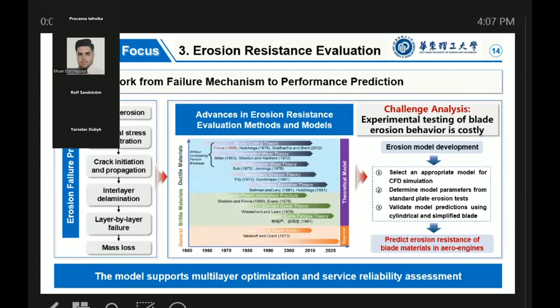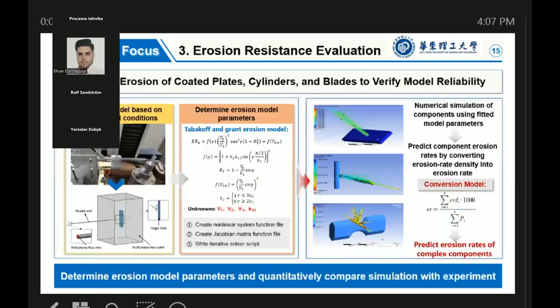After clarifying the erosion failure process, we moved from mechanisms to prediction, because direct blade erosion tests are extremely expensive. We combined multi-scale experiments and simulations to develop a quantitative erosion model, supporting both coating optimization and reliability assessment. Here we developed a numerical model replicating laboratory erosion conditions. Using clean erosion data, the model parameters were calibrated, and the erosion behavior of plates, cylinders, and simplified blades was simulated. And a conversion model was developed to transform erosion rate density into erosion rate, enabling quantitative comparison and prediction for complex shapes.